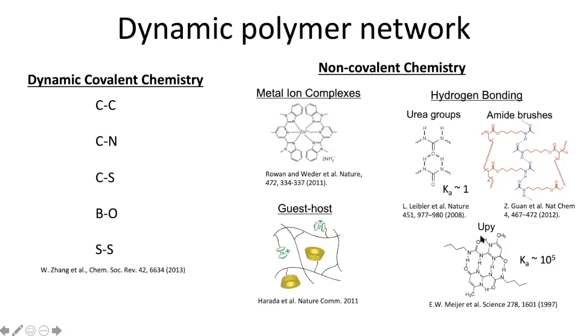For example, the UPy unit pioneered by Bert Meijer has an association constant of 10 to the fifth. It results in a polymer network with solid-like rheological behavior, low dynamics, and high modulus. On the other hand, the association constant of urea is only around 1. The resulting polymer network may be liquid-like if highly flexible polymer backbone is chosen, with high dynamics and low modulus.